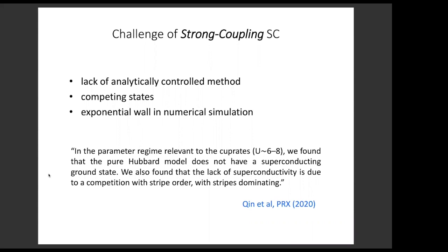For example, in the recent work from the Simons collaboration, it was found that for the pure Hubbard model on the square lattice, in the strongly interacting regime, where U is 6 to 8 times the hopping t, the ground state is non-superconducting, and it's non-superconducting for an interesting reason: superconductivity is suppressed by a competing state, and that is a stripe state. So this illustrates the challenge of handling strongly repulsive systems and searching for superconductivity in such systems. Next slide.